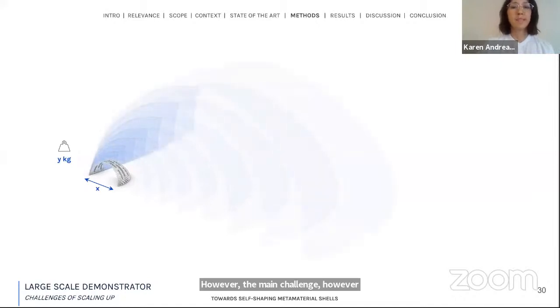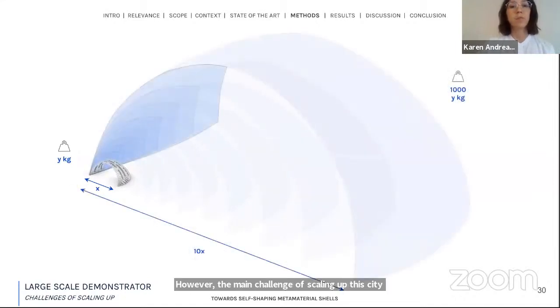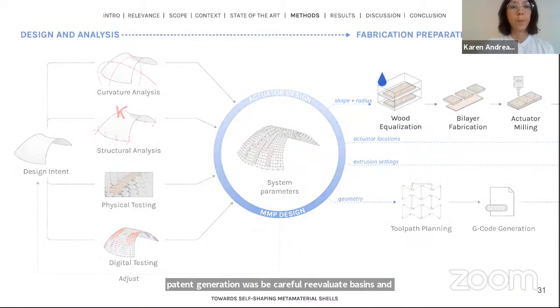However, the main challenge of scaling up this system is the increased self-weight. By scaling up the system 10 times, the resulting structure weighs 1,000 times the initial pattern. Therefore, the bilayer thickness ratio and pattern generation must be carefully reevaluated based on the described workflow.